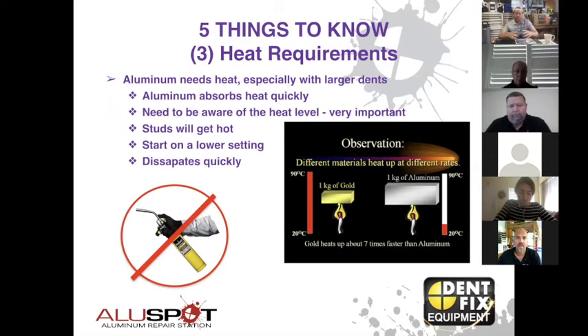The heat requirements for aluminum, I'm not here to give specific temperature ratings. I'm actually going to stay away from that for a minute. I know you don't want to get it anywhere near 600 degrees, because that's where aluminum tends to anneal, and that's where you're going to start to have damage. Aluminum will melt at a very low temperature. 1200 degrees is a melting temperature for aluminum. If you get anywhere near that, you're going to burn a hole in the panel, and you're going to be replacing the panel very quickly. So it's really important that you don't use a torch to heat the panel.